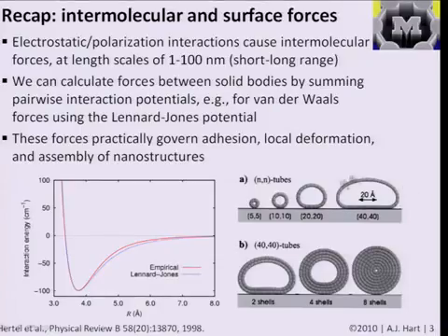So in the case of single-wall nanotubes, this is maybe about a 2 nanometer diameter nanotube, you can get some deformation, some squashing of it, and there's no extra pressure or applied force on the top, but rather it's the atoms of the substrate feeling the atoms of the tube and pulling down on them. And that can have a very practical consequence, sometimes a benefit for things like adhesion and sometimes a consequence for things like processing, for removing nanotubes from a substrate or for debundling them, for example, for separation, as we'll see later on as well.